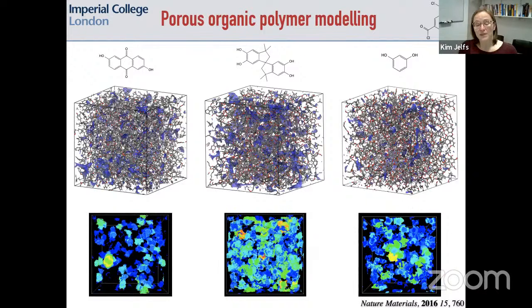So this is an example of three different systems that we modeled very early on using this approach. Three systems all made with a triacyl chloride shown at the top, but with different reaction partners, those three organic molecules shown at the top. In the middle, we have a normal display of the polymer models that you get with the voids shown in blue. And then at the bottom, the different voids are shown coloured by the void size.